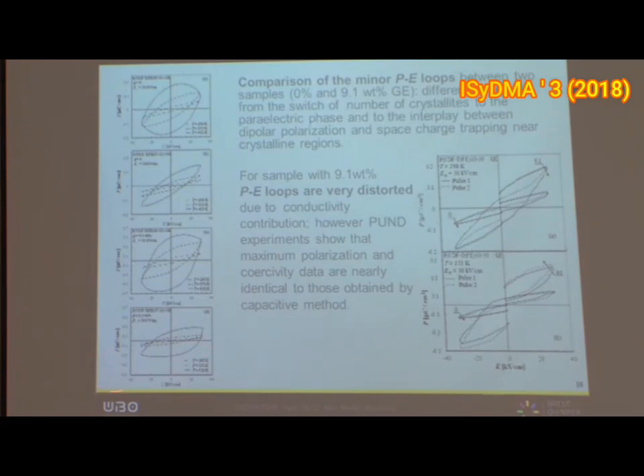So you look at the polarization cycle, which is very distorted, depending on the VDF ratio, depending on the graphene content. And when you did the PUND method, you got exactly the same values of the maximum polarization, the coercivity. So even if these loops are not major, because we don't apply sufficient amplitude of the electric field excitation, you can have a solid, rock solid I would say, conclusion, because the two methods give the same result.